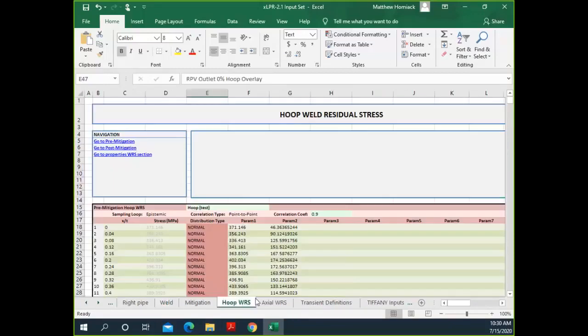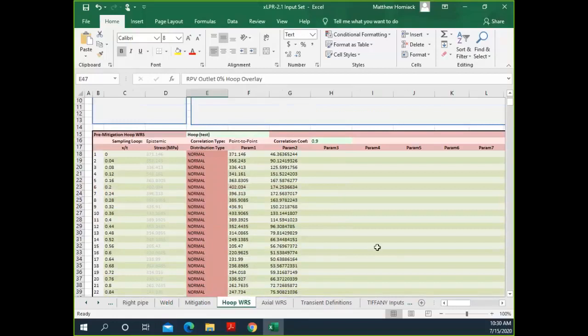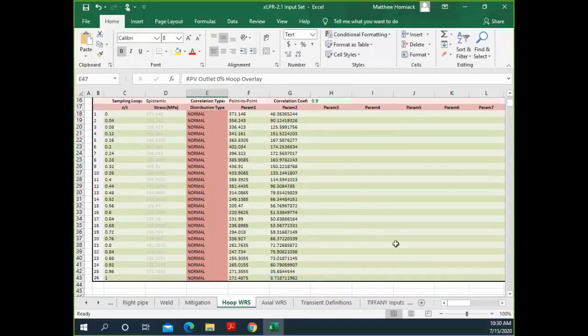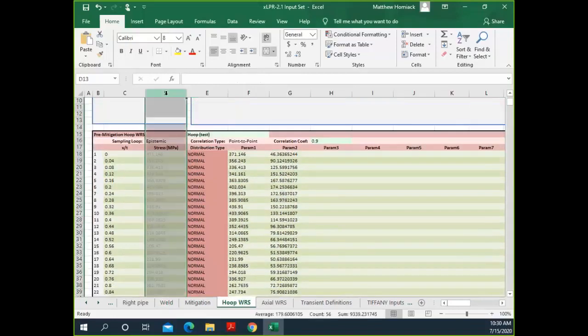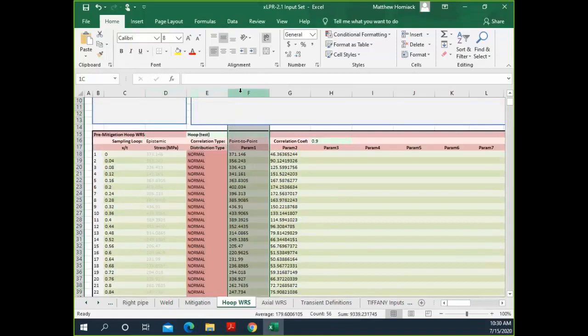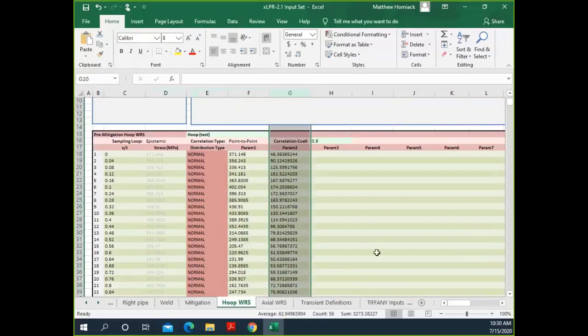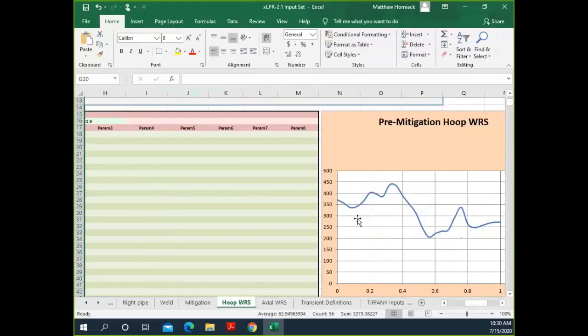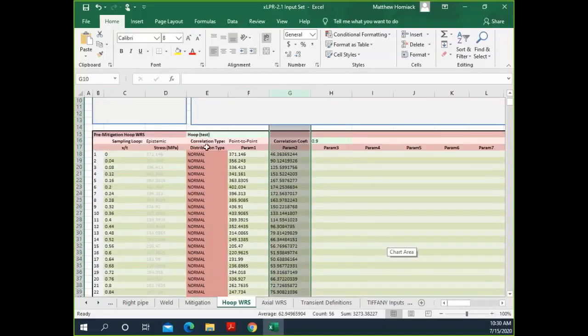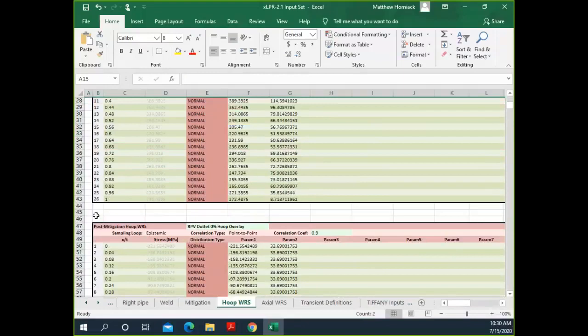The weld residual stress inputs allow defining a WRS profile at 26 points through the thickness in both hoop and axial directions. The profile can be either deterministic or defined as a normal distribution, where parameter one is the mean and parameter two is the standard deviation for each point. Deterministic values on the right show what the profile looks like. Each sheet has profiles for both pre-mitigation and post-mitigation.